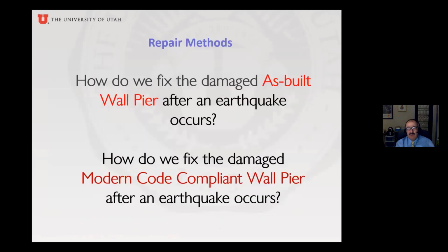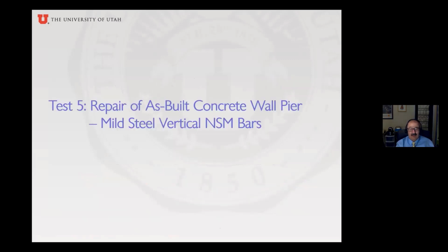So first, we will start with the as-built, the one that was deficient, and we tested it and we failed the lap splice. And we learned something. We learned that if you use the carbon fiber rods as vertical near surface mounted bars, they're great, they're very strong, but they are not very ductile. So we decided to use mild steel vertical near surface mounted bars instead of carbon fiber.